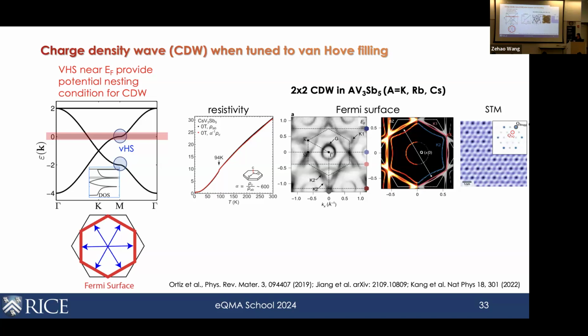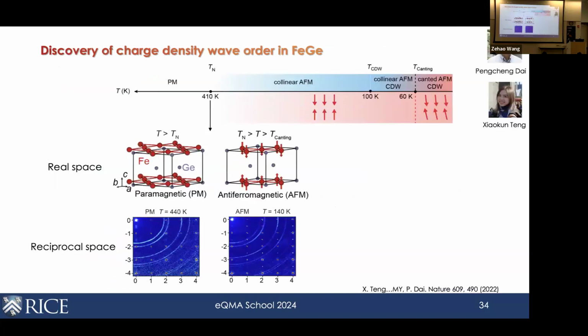Okay, so what about the situation in iron germanium? Iron germanium has been around actually for quite some time. It's not a novel compound. What was known about it is that it exhibits the same kind of A-type AFM order below around 400 Kelvin. Here is work from Pengcheng's group and also our joint student Xiaokun Teng. When they did neutron scattering, they can certainly observe the additional magnetic Bragg peaks up here due to the out-of-plane ordering, right?